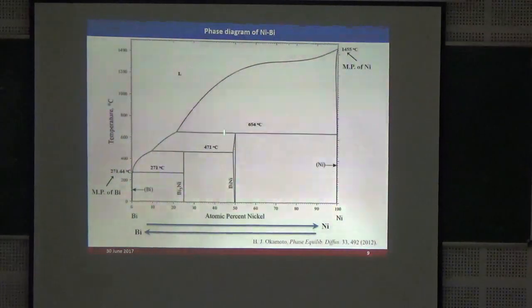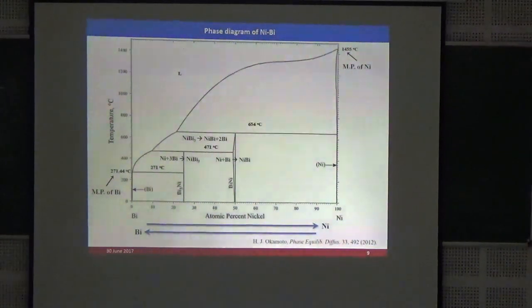Here is the phase diagram of the nickel bismuth system. 271 is the melting point of bismuth, and 1455 is the melting point of nickel. In this direction you have nickel from 0 to 100%. With 25% nickel and 75% bismuth, at a temperature of 271 degrees centigrade, you expect to form the NiBi3 phase. With 50% nickel and 50% bismuth, at 471 degrees centigrade, we expect the NiBi phase. After this temperature, NiBi3 will decompose into NiBi plus bismuth, and above this temperature NiBi will exist but NiBi3 will decompose.